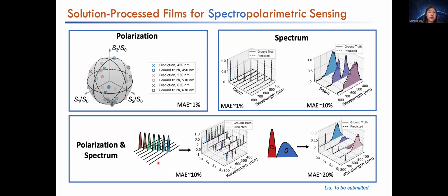What is very special and unique to this project and this material is that we combine the polarization and spectrum. We can still tell the polarization and spectrum simultaneously with very high accuracy. We further tested mixed polarization with a very broadband spectrum, and we can still keep a relatively good accuracy. This has not been measured by previous systems or previous compact systems.